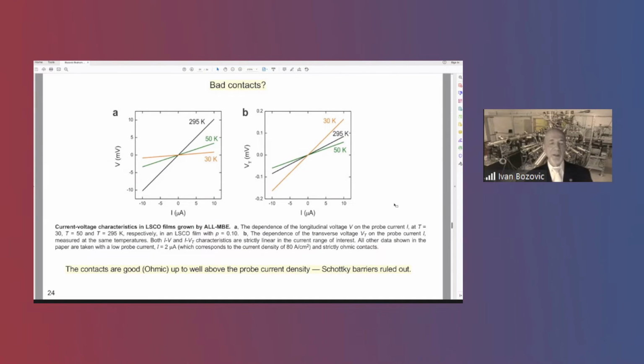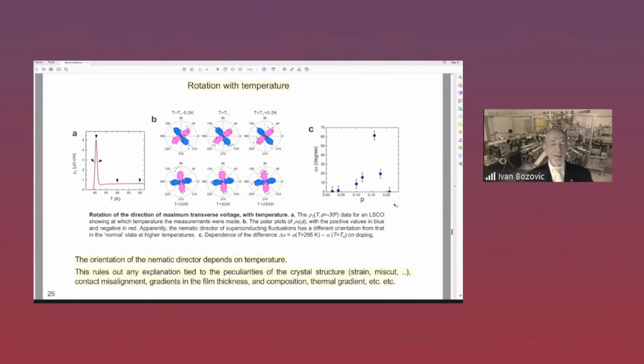So we have ruled out the contact misalignment, but are the contacts ohmic? Schottky barrier contacts could fool you, as people who do this type of measurement know well. And for this reason, we check this routinely for each contact, longitudinal or transverse, in each of the thousands of devices that we have measured. And all the contacts are indeed ohmic, and the contact resistance is in fact quite small. This may sound simple, but it took much experimentation until we developed a robust recipe to fabricate low resistance ohmic contacts to cuprate films.